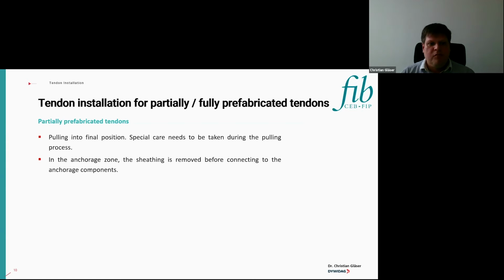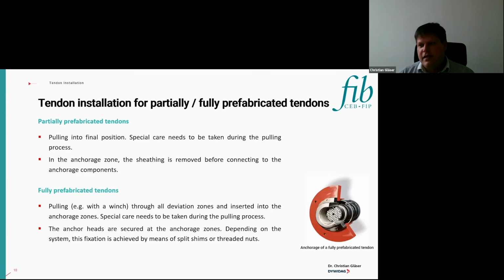Coming now to the partially prefabricated tendons, usually they are pulled into the duct. So here, of course, it needs to be considered that the duct is not damaged during this pulling process. And in the anchorage zone or close to the anchorage zone, the sheathing is removed before connecting the partially prefabricated tendon to the anchorage. In case of the fully prefabricated tendon, installation is quite similar. So that means, again, pulling, considering that we are not damaging the duct.